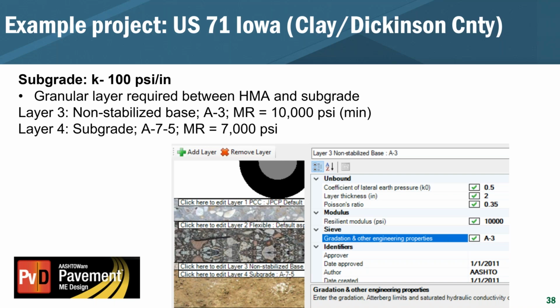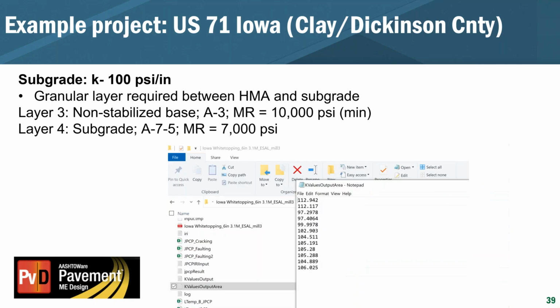Now, how do I find out if I was successful in doing that? Well, if I can get this to progress forward, what I did was go into the supplementary files that are created by Pavement ME. And if you go into the K value outputs, as you see right here, and click on that file and open it up in Notepad or something that reads a text file, it will give you the K value that it estimated throughout the year. And so you see in the spring thaw or the recovery periods, it was a little bit below 100. For the majority of the year it's pretty close to 100, and then after that, for a couple of months, it's about 111, 112. And so I figured this is probably a pretty good representation of that 100 PSI.